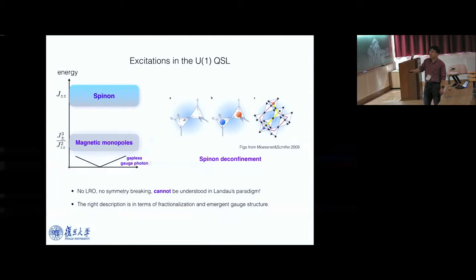But imagine you flip one spin, you create defect tetrahedra. Because the spins are strongly fluctuating, you can actually separate these defect tetrahedra by an arbitrary distance without costing too much energy. Because the spins along the pathway are strongly fluctuating, the string connecting these defect tetrahedra has no tension. You can fluctuate this string arbitrarily. In other words, this is actually Xiao-Gang Wen's example of a string-condensed phase. The end of an open string is a particle, and the closed strings are strongly fluctuating. They give rise to this emergent U(1) gauge photon. This is another way of understanding it.